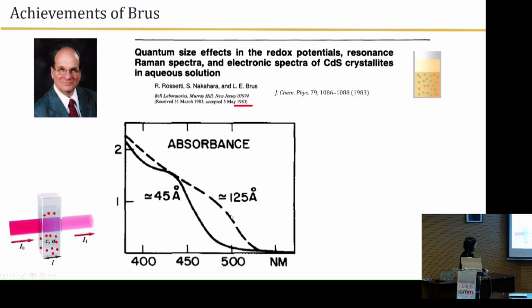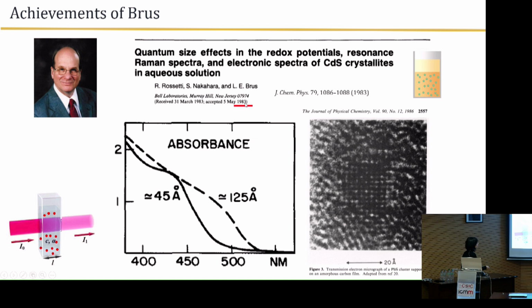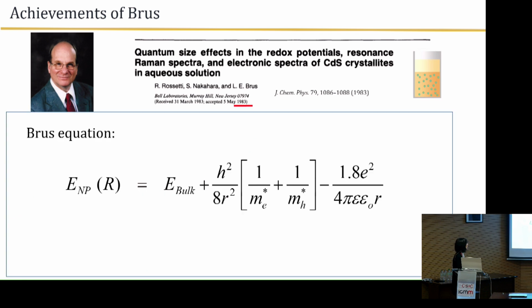And by transmission electron microscopy, he could understand that this difference in the absorption edge was related to the mean size of the particles in the colloid solution. In this paper, he didn't include these TEM images, but he did it for other systems years later. Another of the legacies of Brus is what we call the Brus equation. It's a simple expression that gives us the tools to predict the optical properties of the particles depending on their size.